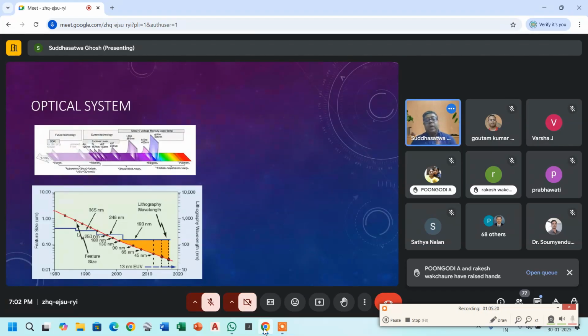After which the systems which use 193 nanometers were used to make feature sizes like 90 nanometers, 65 nanometers, 45 nanometers. And subsequently, when this shrinking down was not possible, people still made features smaller than 45 nanometers using these deep ultraviolet systems, like 22 nanometers or 16 nanometers. But there was a limit which was reached. And then people invested in much lower wavelength, which is the extreme UV, as we call it, which is near to the X-rays in the optical wavelength spectrum,